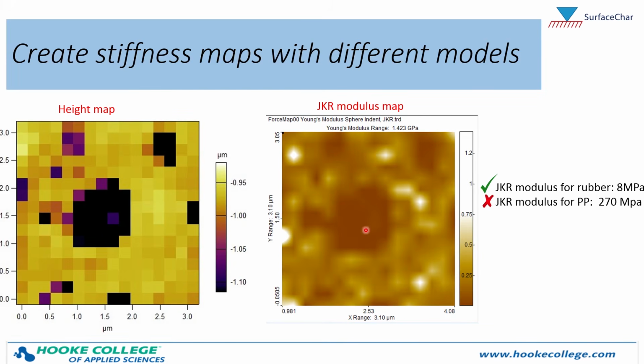Now the cantilever spring constant has to match what we call the contact stiffness of the material, which is related to the actual properties of the material. For this measurement, I tuned the spring constant of the cantilever to the contact stiffness of the rubber because I want to make sure I got an accurate value for the rubber. But because there's such a large difference of several orders of magnitude between the moduli of these two materials, by tuning my spring constant to the rubber, that spring constant was not going to match the contact stiffness on the polypropylene, and therefore I wouldn't correctly measure it, which is exactly what happened.